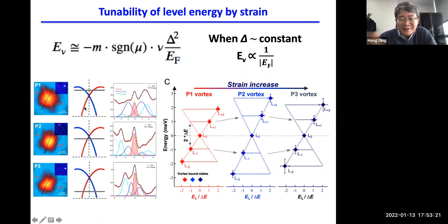In both cases, you will see it. As Pierce showed in his PRX, TDS can also show Majorana if you break the C4 symmetry. In this case, we only showed the Dirac cone for the TI point. For the 110 direction, the pressure of the strain actually moves down the Fermi energy continuously, so we reach the pure TI phase. This is easy. But if we apply the 100 direction, we actually move up the EF, so we can move toward this TDS phase.